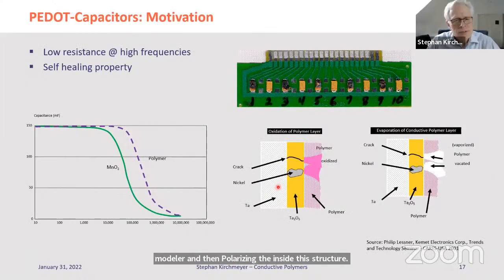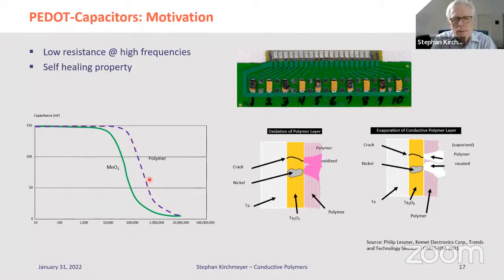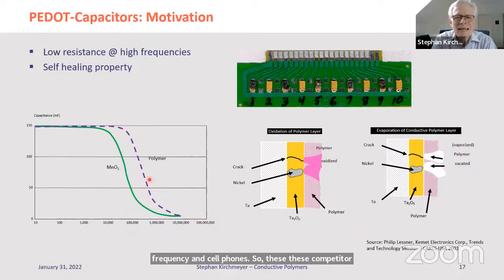Why did people do this? Basically for two reasons. One reason is shown here. If we look at the capacitance versus frequency, you can easily see that manganese dioxide has a problem around, let's say, 30 to 50,000 hertz. While polymers, and the higher the conductivity of the polymer, the further this curve is shifted to the right side, could easily work up to 1 megahertz. And that was very important to generate capacitors which were used either in computers, which had higher and higher frequency, and cell phones. So these capacitors were definitely one of the keys to get cell phones more and more into the market.